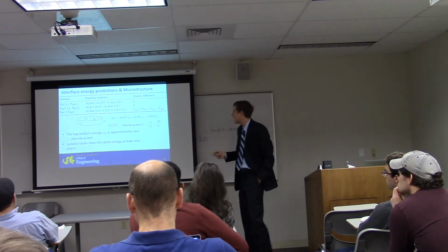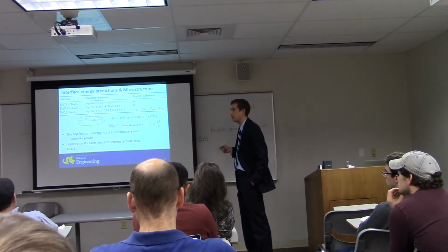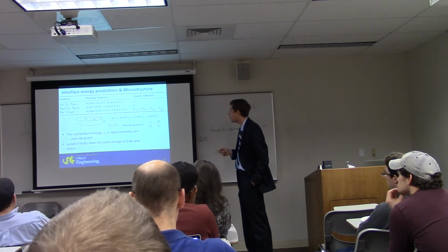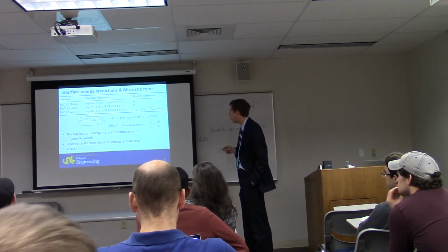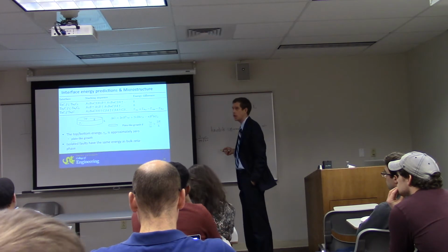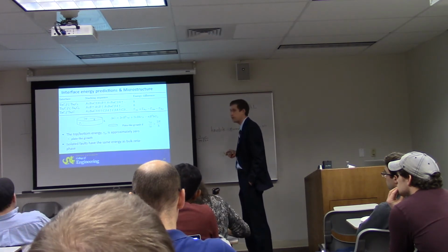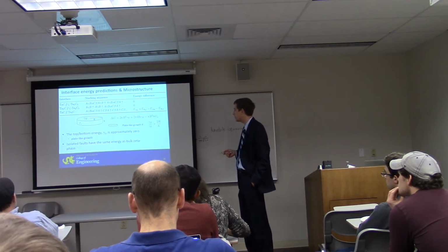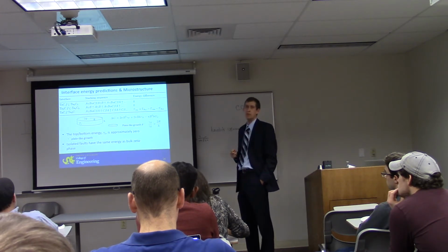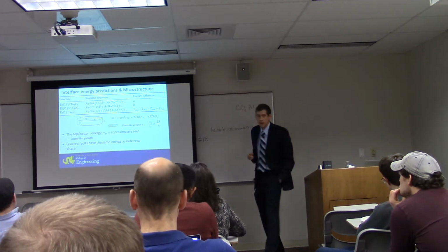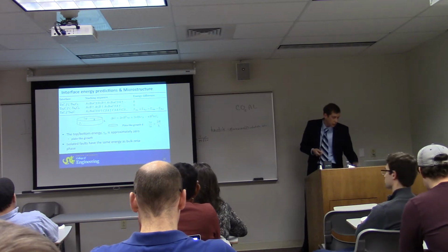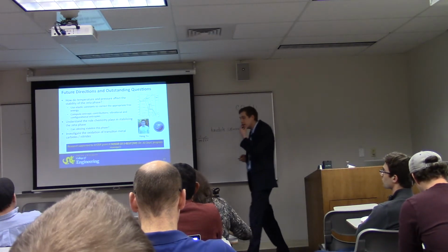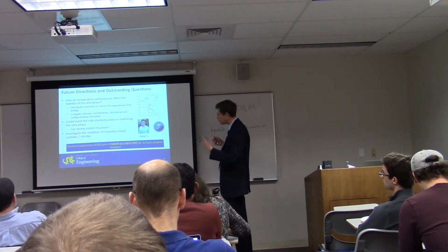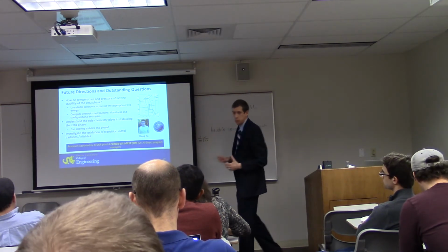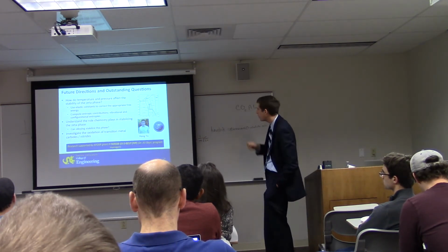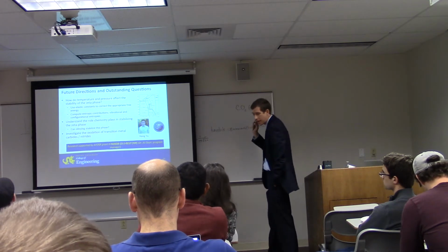So that hits all of the points that I wanted to make, which is that the top and bottom energy is zero, which will force plate-like growth. Not only that, but an isolated fault is not really any worse off than a bulk zeta phase energetically. And so that gives us a lot of insight into why this microstructure appears. We'd like to go back and back that up with phase field modeling if we can, but I don't think it's really going to change my answer.